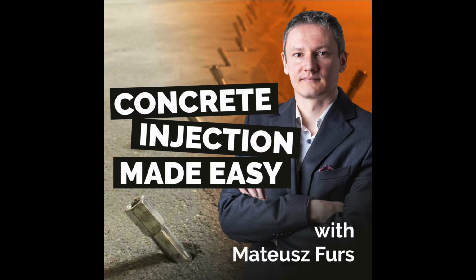Sometimes we don't make the curtain itself, but we inject into the structure of the masonry, because if we have like 80 centimeters to 1 meter of it, it's quite a big volume of masonry, so it can be filled with this resin. And this is my favorite way of water tightening structures, because the consumption of the resin is lower, and there is better control over the material. We can easily see where it is coming inside the wall, because it goes through other packers in this whole area. So this is the way I do it. It's cheaper also for the investor, so they like it as well.